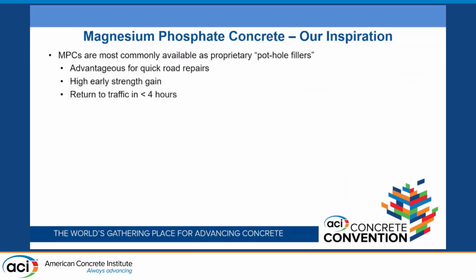And so magnesium phosphate concrete, our inspiration for all this, these are commonly pothole fillers, is what I call them, because they're so rapid setting. You really can't work with them. Most times they come in a 5-gallon bucket, pre-blended. You've got your handheld mixer and you mix it and you're filling a pothole with it. You get high early strength gain, and it's used by a lot of DOTs because you can return the traffic in less than 4 hours.